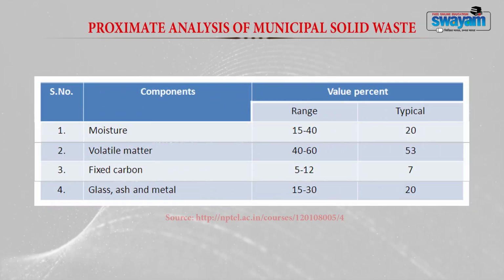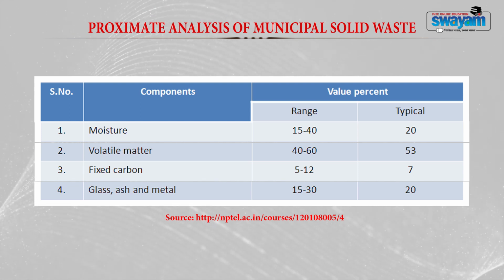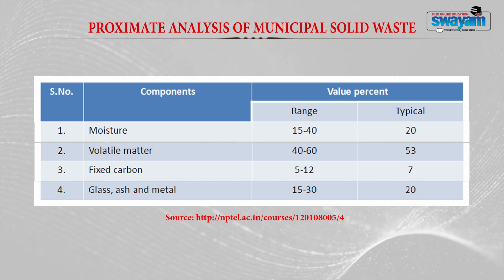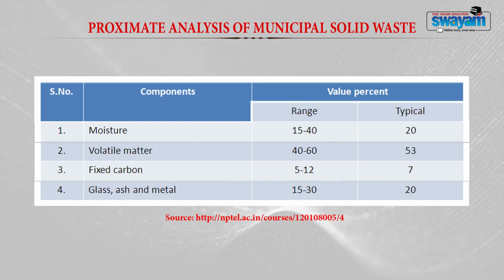This table provides the proximate analysis of municipal solid waste. In this table, a typical municipal solid waste contains a moisture content of 20%, volatile matter of 53%, fixed carbon of 7%, and glass, ash and metal of 20%. Another parameter is the fusing point of ash. The fusing point of ash is the particular temperature at which the ash resulting from the burning of waste will form a solid clinker material due to fusion or agglomeration. Generally, the fusing temperature for the formation of these clinkers is 1100 to 1200 degrees Celsius.